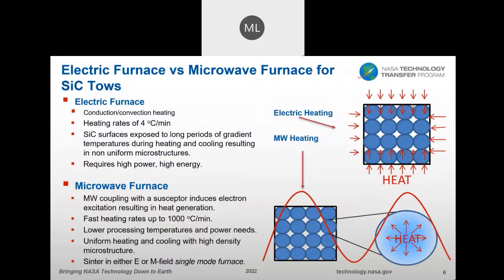So before we move on, let's take a look at some of the differences between the electric furnace and the microwave furnace, particularly for this type of material and structure, because they are thin fibers. In the electric furnace, you mainly have conduction and convection heating, with slow heating rates, 4 degrees per minute, and the silicon carbide surface is exposed to long periods of temperature gradients as the temperature is ramping up to the heat treatment, or whatever process you are doing on the fiber, and then the cooling process. And that leads to non-uniform microstructures. And typically it requires high power and high energy to accomplish this.